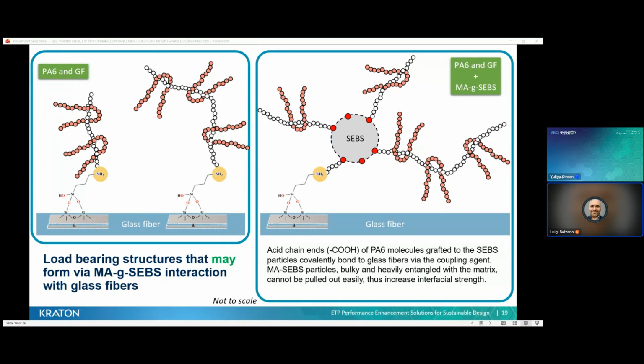Such a mechanism leads to a very high interfacial strength because of the size of the SEBS particles, they are very bulky, and the many entanglements that it forms with the surrounding. Eventually, this leads to an improvement of the macroscopic mechanical properties of the material. In summary, looking at the picture on the right, the basis for the observed improvement in tensile properties is the local interaction between the maleated SEBS and the coupling agent on the glass fiber.